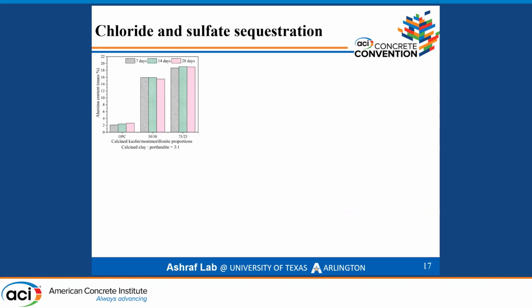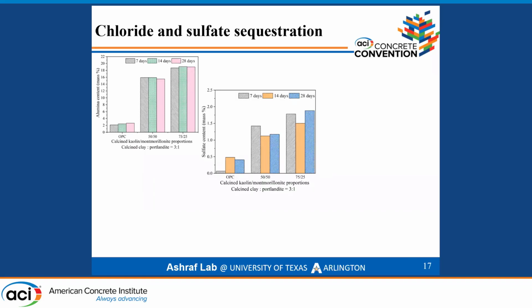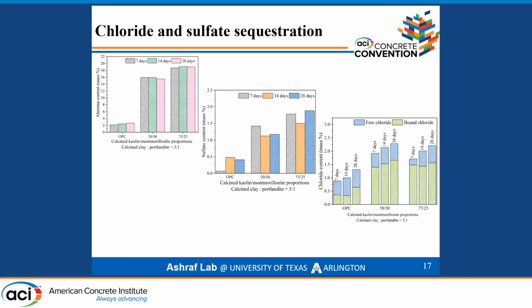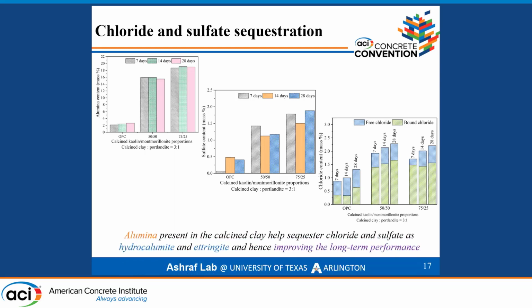In order to determine the chloride and sulfate sequestration, we compared our clay binders with the OPC system. This plot represents the alumina content present in our system. As you can see, there is a lot more alumina present in the clay system than in the OPC system. This alumina from the clay reacts with the sulfur and calcium from the Portlandite and forms some ettringite. That is how it is binding the sulfate. And again, the alumina from the calcined clay also binds chloride by forming hydrocalumite. That is why the total chloride and bound chloride content is really high compared to the OPC system.